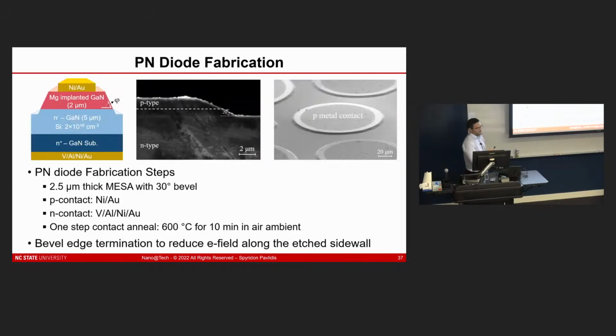So again, I want to see a device. What I showed you previously is a lot of the material science behind it, but I want to make a device. And one of the first devices we made was actually just trying to make a PN diode. So we did this now on a conductive GaN substrate, implanted magnesium, annealed it, and then made a truly vertical GaN diode where we're making a backside contact. Another feature of this design here is that we created beveled edges. These are low sloped edges of the device, and if you go through the design and engineering of these types of devices, that helps to distribute your electric field and bring it in from the surface so that you can really leverage the bulk high critical electric field of GaN.